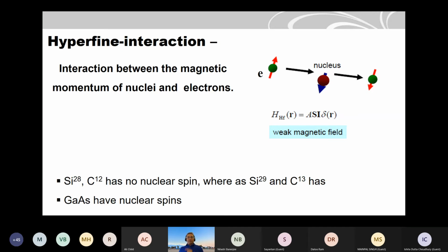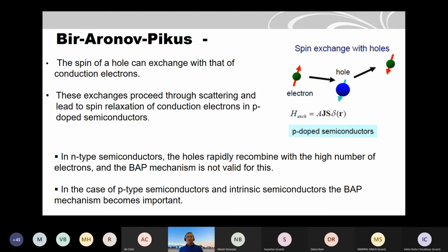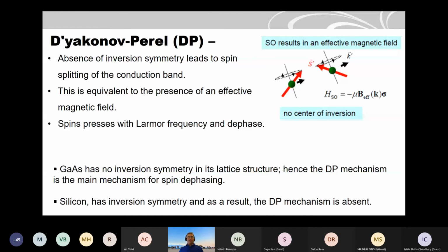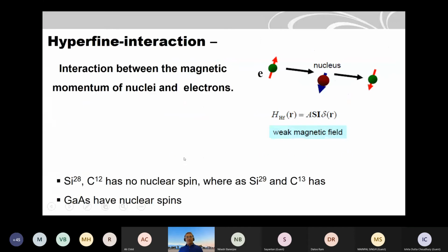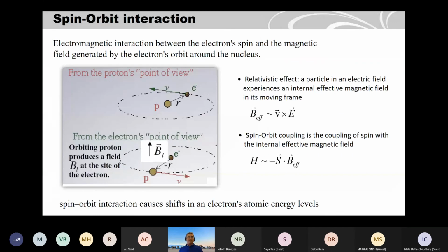So what is the main mechanism, as you see here, that will be useful for spin control of spin polarization? It is a material where inversion symmetry is broken, or a material with a high spin orbit coupling. In such a material it is actually very difficult to get spin transport because the spin orbit coupling is very large, so it is also difficult to get spin transport up to room temperature.